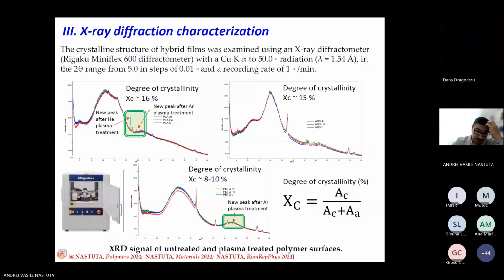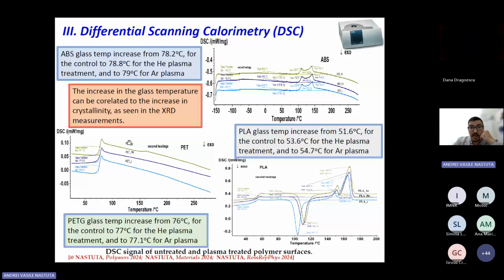What was interesting for us was to see if the bulk material is changing, and for our surprise, we saw that after the treatment, some new peaks can be found in the X-ray diffraction pattern. We're still trying to understand what these new peaks are, so still under evaluation. But also we saw that even in the differential scanning calorimetry characterization, we have some differences. Small, but enough to say that the overall melting temperature of the materials is changing after the plasma treatment. And this can help us with the cost effectiveness of the material for 3D printing.